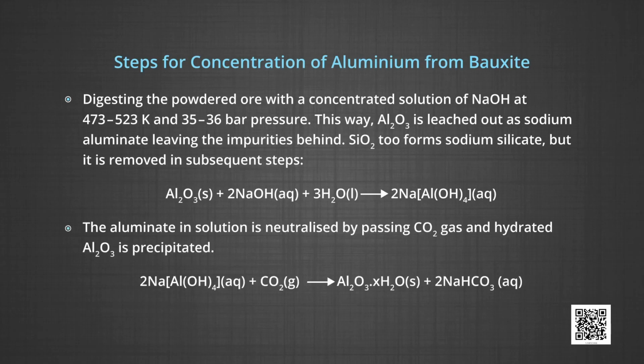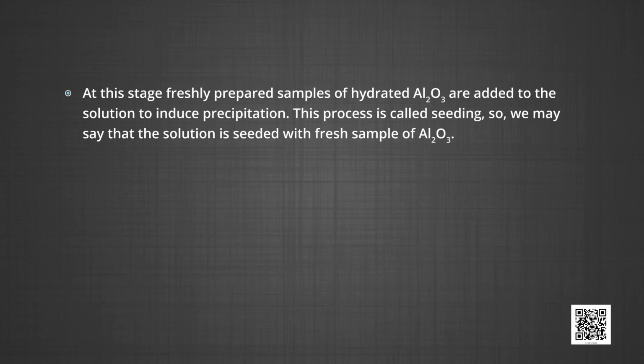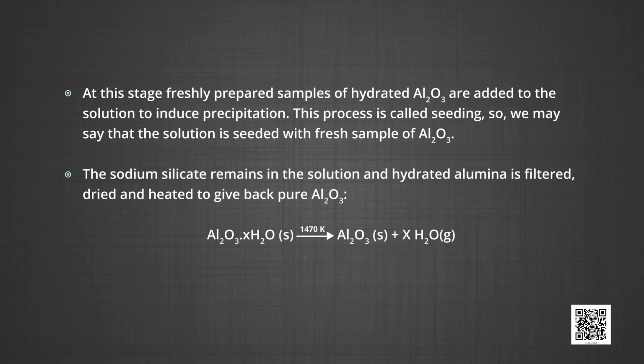In the second step, the aluminate in the solution is neutralized by passing carbon dioxide gas and hydrated alumina is precipitated. At this stage, freshly prepared samples of hydrated alumina are added to the solution to induce precipitation. This process is called seeding. So, we may say that the solution is seeded with fresh sample of alumina. In the fourth step, the sodium silicate remains in the solution and hydrated alumina is filtered, dried and heated to give back pure alumina, that is Al2O3.